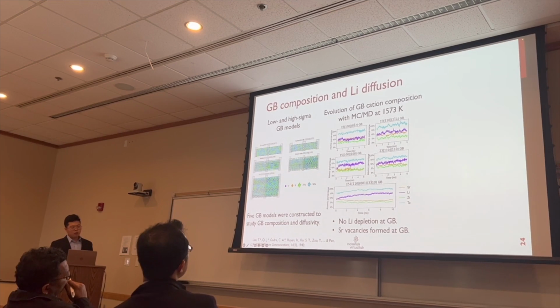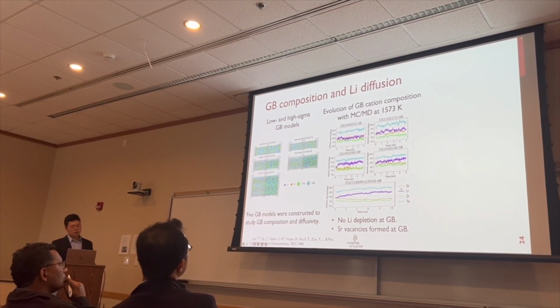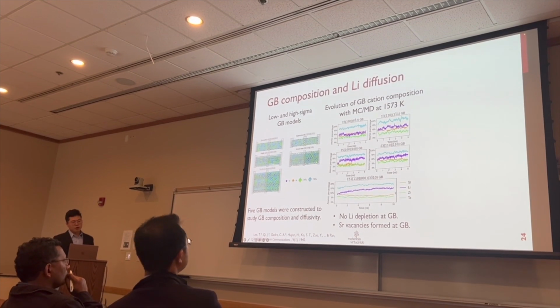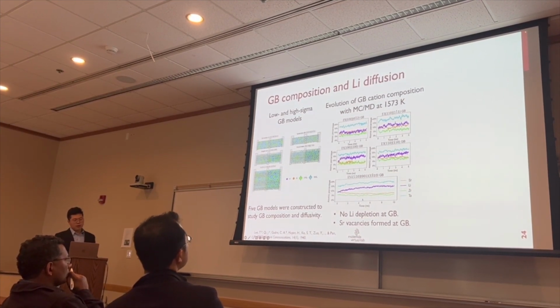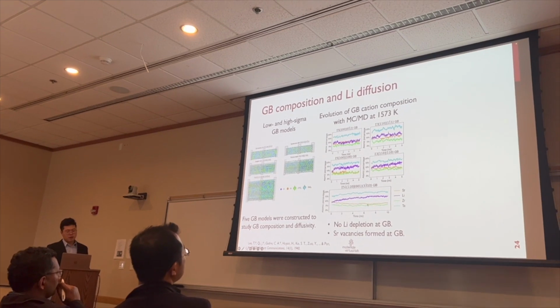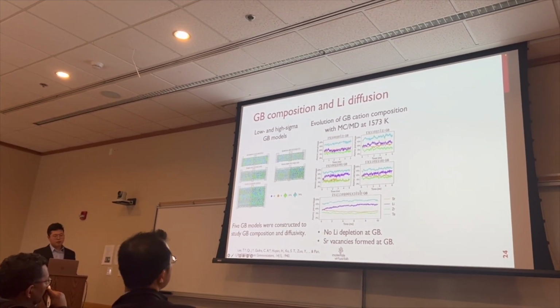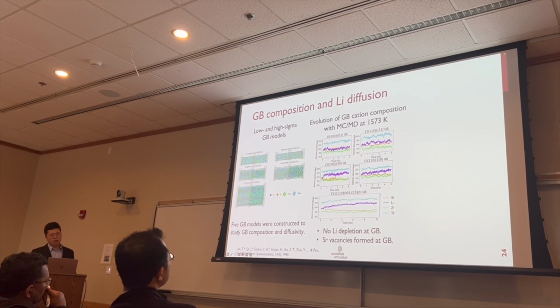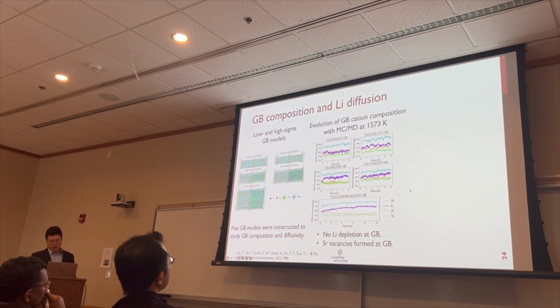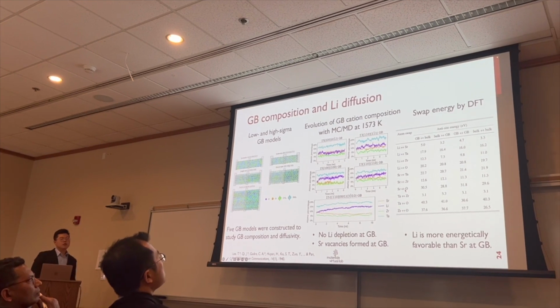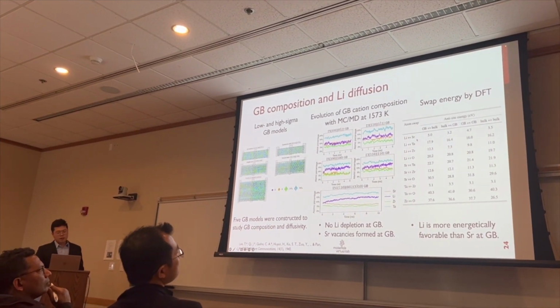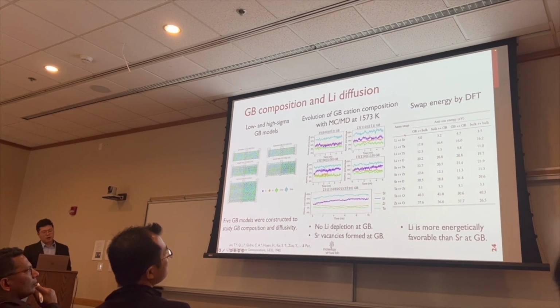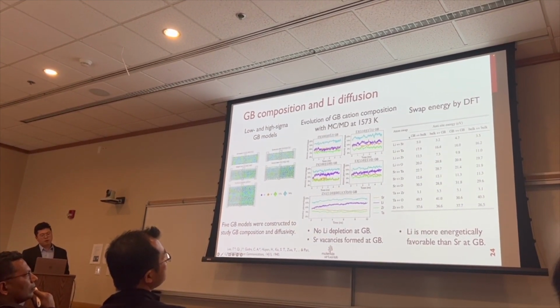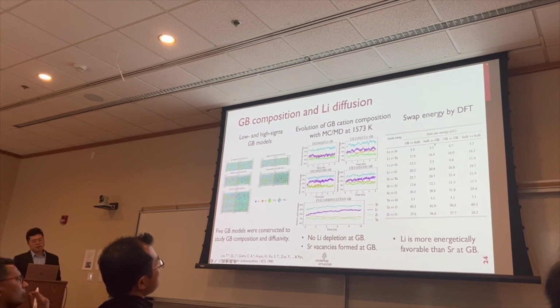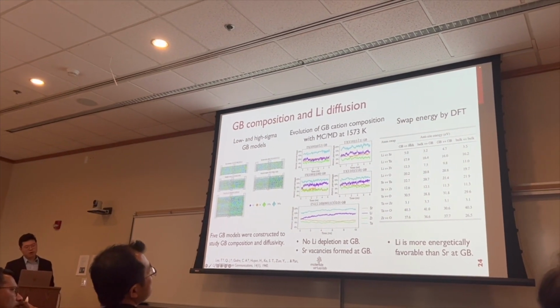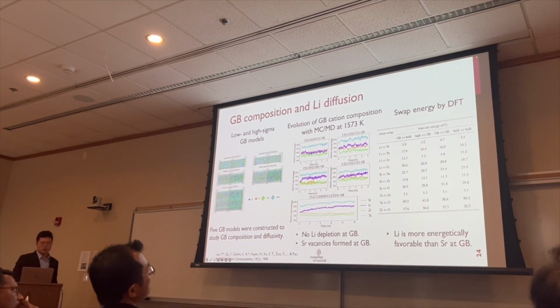And you can see that for all those 5 systems, we don't see any lithium depletion at the grain boundary. Actually, in the lower three cases, there is some increase in the lithium concentration at the grain boundary, which is accompanied by some formation of strontium vacancies at the grain boundary. And by checking the swapping energy by DFT, looking at the first line of lithium and strontium swapping from the grain boundary region to the bulk region, we can see that lithium is more energetically favorable than strontium to stay at the grain boundary for this material.